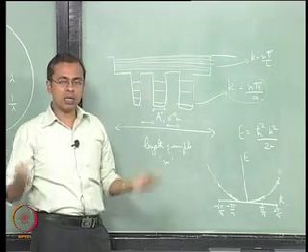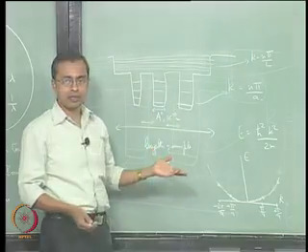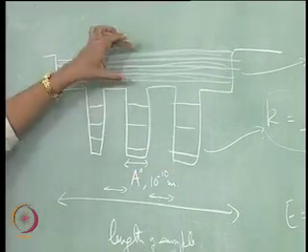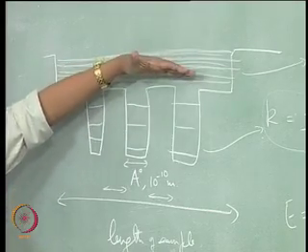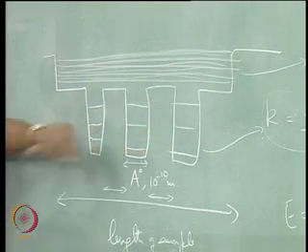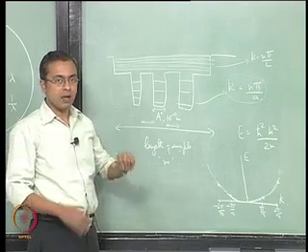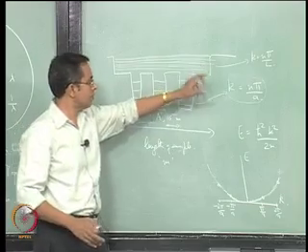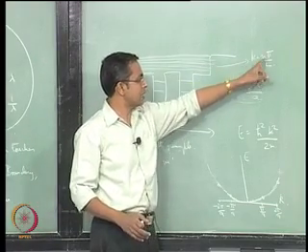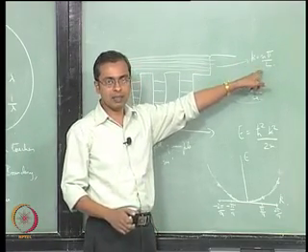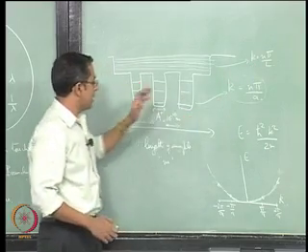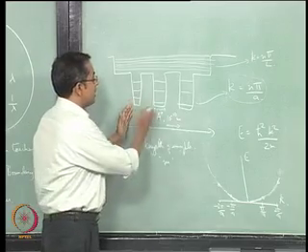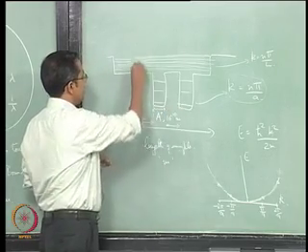The issue that we had not accounted for so far was that we never bothered about the structure. When we simply said the number of free electrons per unit volume, we treated these nearly free electrons as though they were not affected by the presence of this periodic structure. What we now recognize is that there is a wave vector associated with these nearly free electrons, and the allowed wave vectors are given by this information here. Those allowed wave vectors can and will interact with the periodic structure that is defined by these locations.